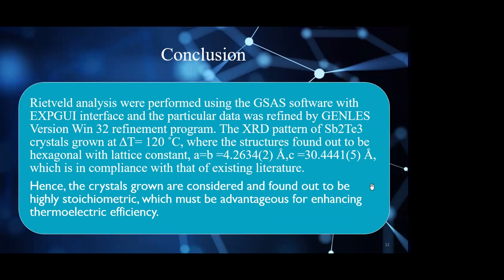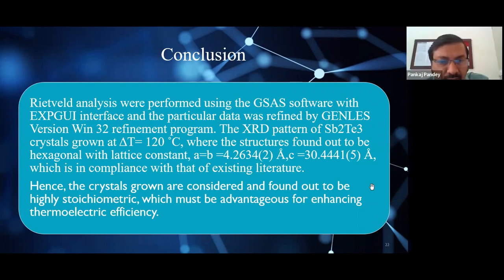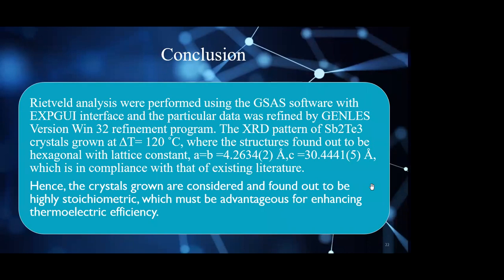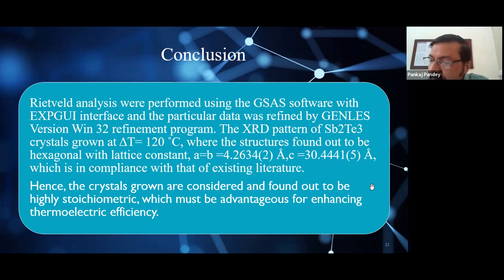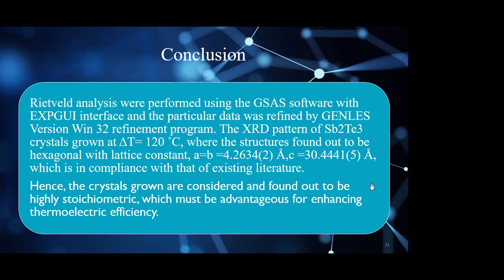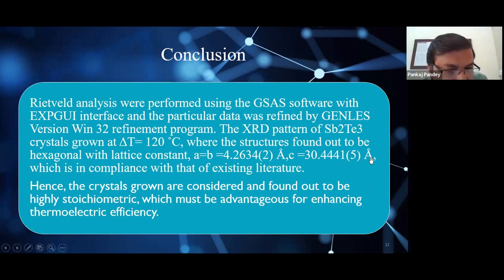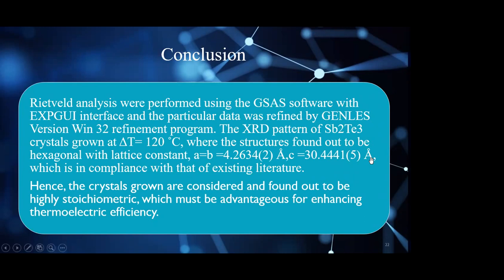You have written here the XRD pattern of Sb2Te3 crystal grown at delta T 120 degrees centigrade. So what are the different temperatures? This is delta T, no? So what are the different temperatures you have taken for your study? Compared to the room temperature and the temperature of the crystal. How much is it? It was grown at 120 degrees Celsius, sir.